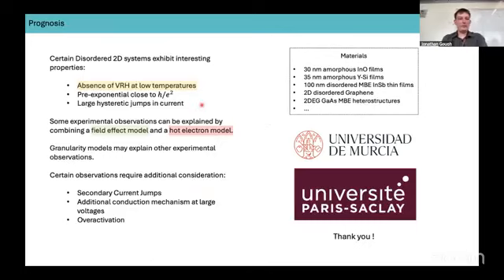Okay, so I'll just give a very brief summary. The work that I've been doing at UCL is looking at these disordered semiconductor systems, typically indium antimonide thin films. And what we noticed was that for weaker disorder, we observed this absence of variable range hopping and instead this simple activated regime. Along with this came these large hysteretic current jumps, which we modeled by this hot electron model and the field effect model.